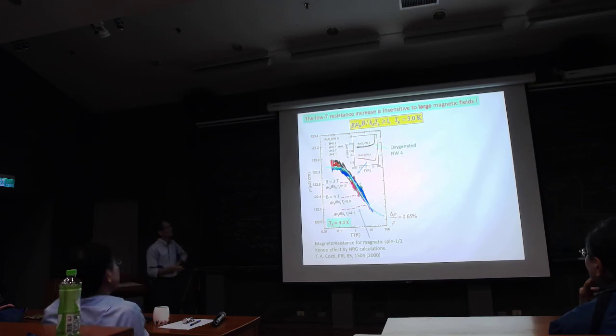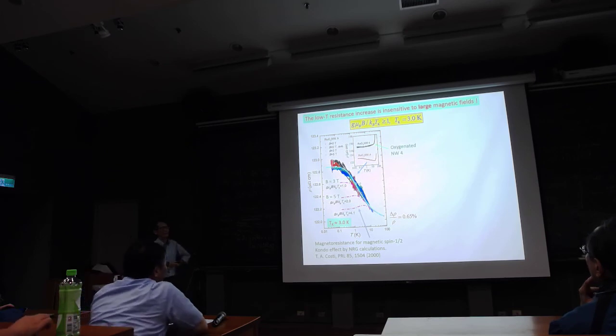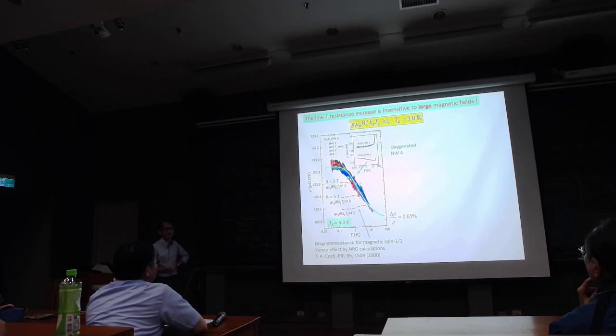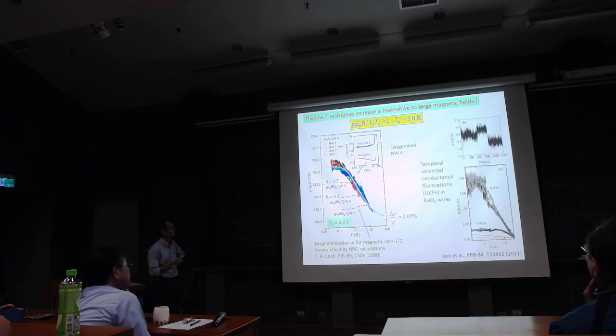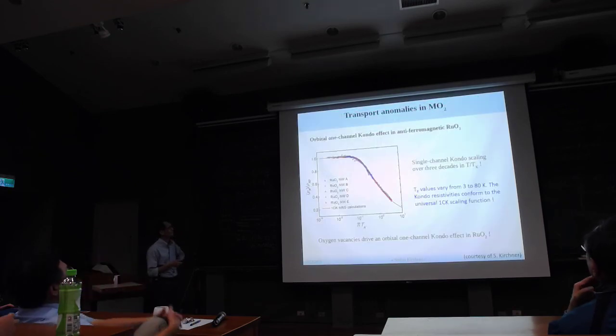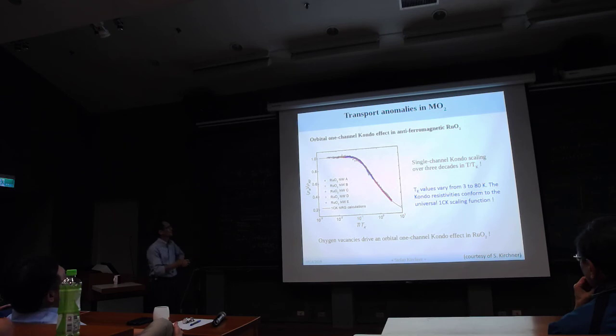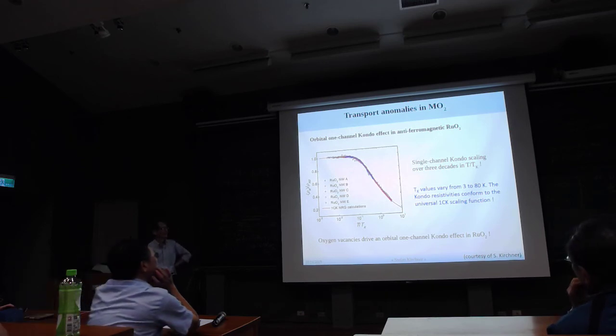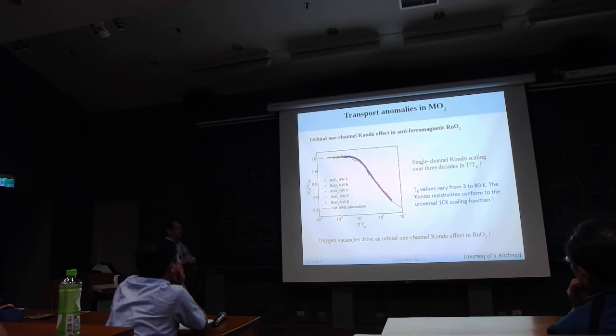So in this case, because the material is weakly antiferromagnetic, time reversal symmetry is broken. So we go back to the one channel Kondo effect. We actually have a few wires, and the Kondo temperature varies from 3 to 80 Kelvin. But if you plot the reduced temperature against the normalized Kondo resistivity increase, it collapses very nicely over 3 decades of temperature.